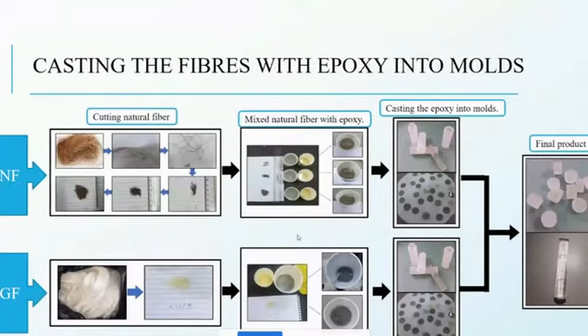For the manufacturing of the natural fiber, as we said, we dry the fiber and we do some cleaning, use it in an ethanol bath, and we cut it to a certain length. Then we use the sonicator to mix the resin and the hardener with the epoxy until we get it to the final shape, even for the small punch test or for the Brazilian. For the glass fiber, we did the same way. We just cut it to the certain length that we need.